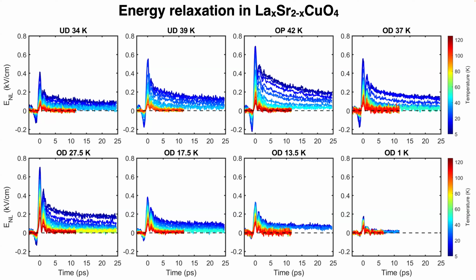So it's very different than the rate that I told you about before, which was the rate in the context of transport, which was the rate that current dissipated, effectively the rate that momentum leaves the electronic system. This is the rate that energy leaves the electronic system. And so it's sensitive only to the class of scatterings that remove energy from the electronic system, which in a conventional picture is just phonons. So it's a measure of the electron-phonon coupling and a quite precise one.